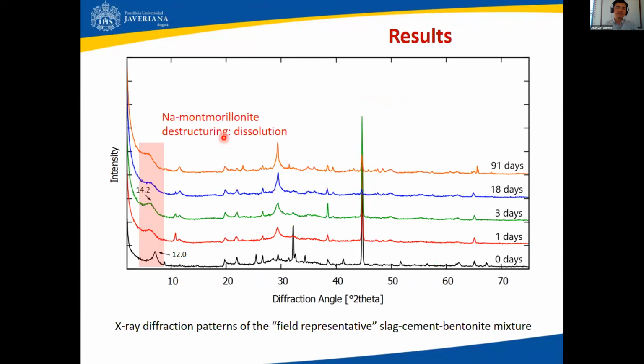So, as promised, I'm gonna explain the data separately just to identify the different minerals that we found. So, first of all, in both mixtures, in the field representative and the spiked mixture, we found, of course, sodium montmorillonite in the very first state, in the dry state at 0 days. However, we confirmed the findings of Mitchell and many other researchers later. You can see here that during the first days, pretty rapid during the hydration process with slag and cement, the peak of bentonite is no longer a peak. It becomes a hump. And in fact, it tends to shift a little bit to the left-hand side.